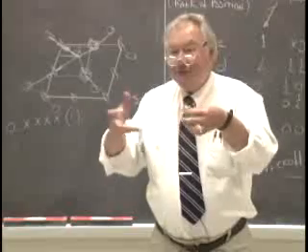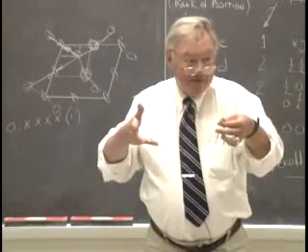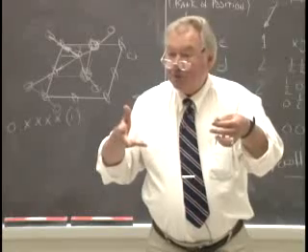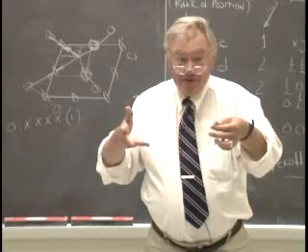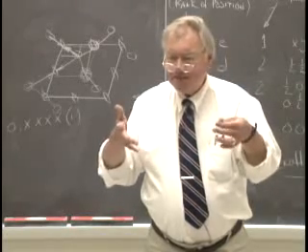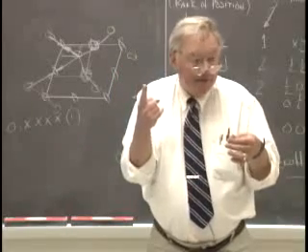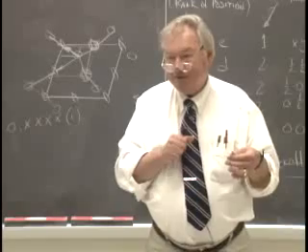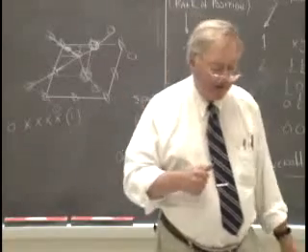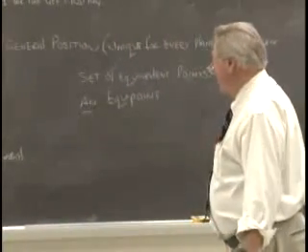And that means the configuration of that molecule is going to be limited to having to conform to a twofold rotational symmetry. So just from the density and the lattice constants, if you find there's one molecule per cell, you know that molecule has to have twofold rotational symmetry. So you can say something about the structure of the molecule. So there are lots of ways in which the symmetry information has something to say about the arrangement of atoms in the structure.